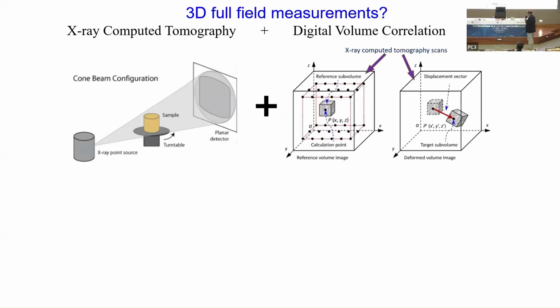Now, once you have reconstructed the volume, and you reconstruct the volume in the undeformed and the deformed state, here you have this undeformed volume, here you have the deformed volume. And you basically are going to try to match how a particular element, which I'm showing here by a cube, moved from the undeformed volume to the deformed volume. And if you can get hold of that mapping, of course, at that point, you've got hold of a strain field or a full displacement field, and you've got everything there.